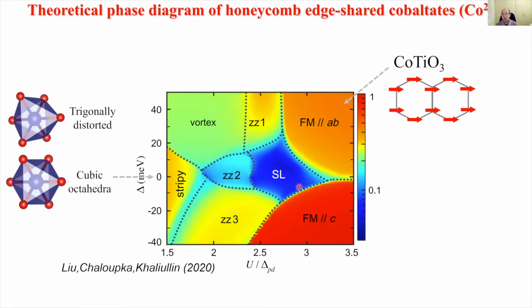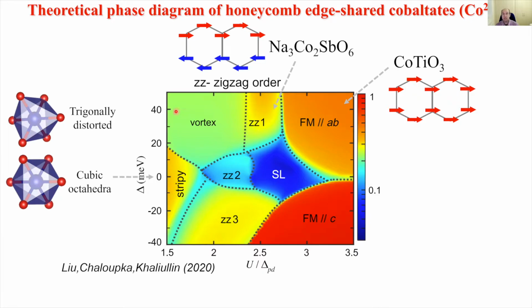Now, the material we're going to explore is in this orange corner of the phase diagram, corresponding to ferromagnetic alignment in each honeycomb layer with spins in the AB plane. Now, if we were to go to the red region here, this would also be ferromagnetic, but with spins along the z-axis. And both of these phases would be expected to have topological magnons. Now, there are other ordered phases in this phase diagram. For example, ZZ stands for zigzag order, where spins form alternating zigzag chains oriented one way and alternating the other way.